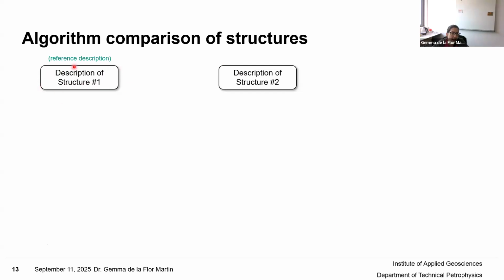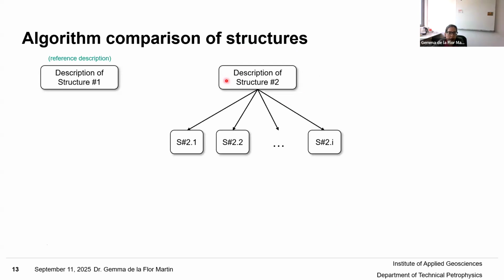The first one is always kept as the reference, and the program first calculates all the symmetrically equivalent descriptions of structure 2, and tries to find among those the one that best matches the reference structure. Each of these equivalent descriptions is specified by a coordinate transformation described by a matrix-column pair that is obtained by combining elements of the affine and the Euclidean normalizer.